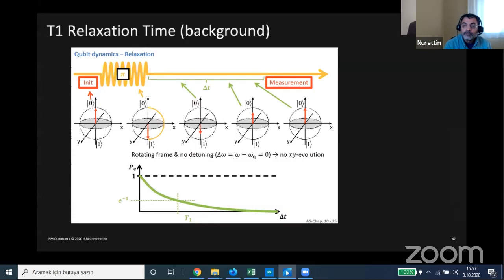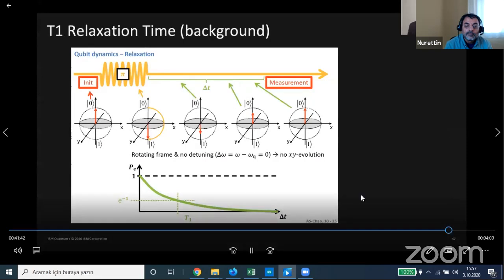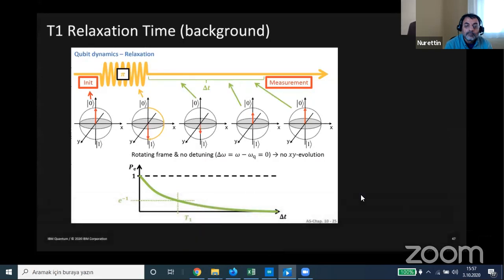So shown here is the Bloch sphere. We initialize the qubit in the 0 or ground state. We apply a pi pulse, which rotates the 0 state around the Bloch sphere to the 1 state, as shown here. This is through this pi pulse, which is a microwave pulse at the resonance frequency of the qubit with a time duration and amplitude just right, and we calibrate it to achieve this pi rotation.